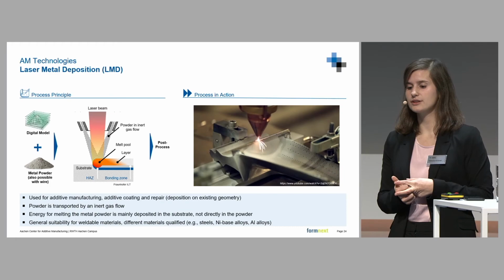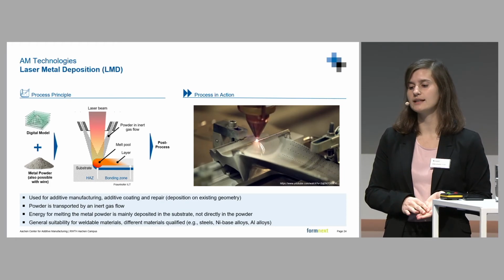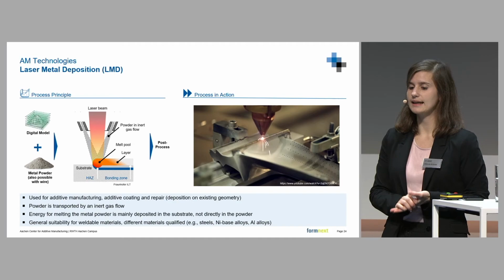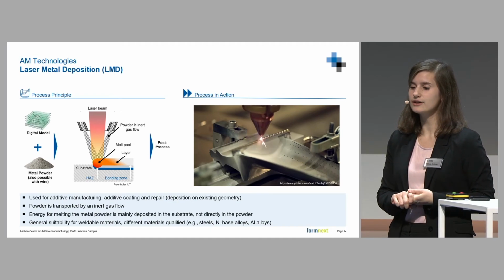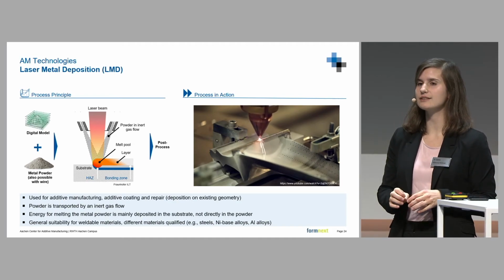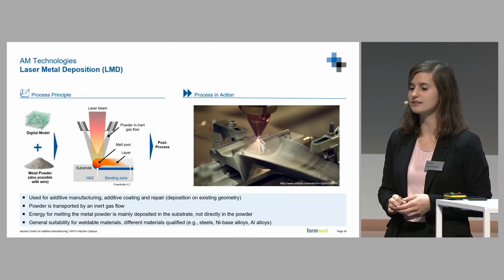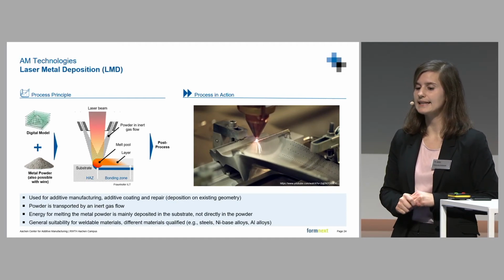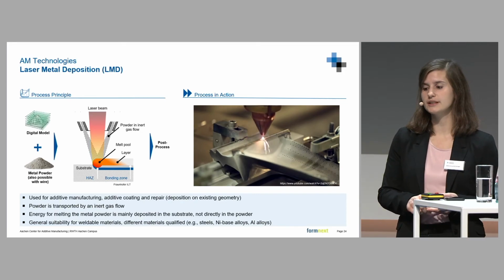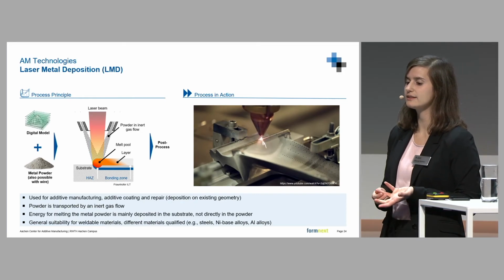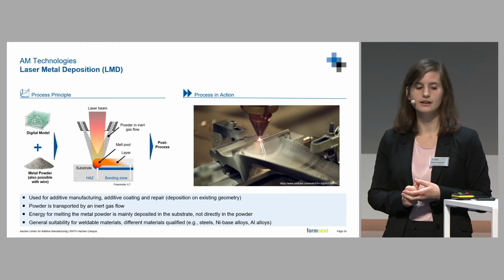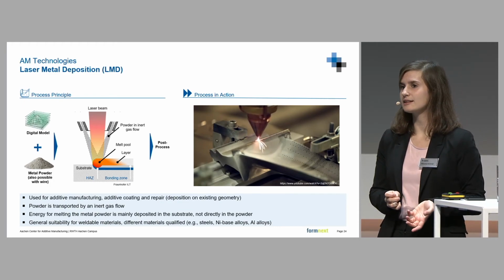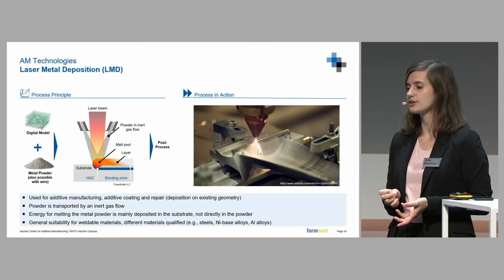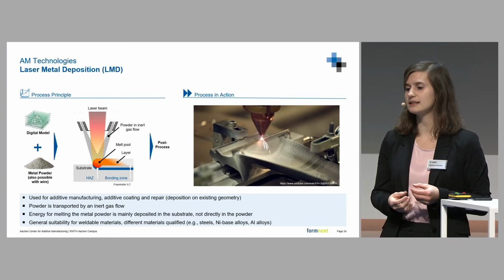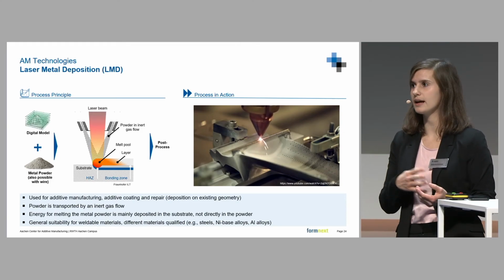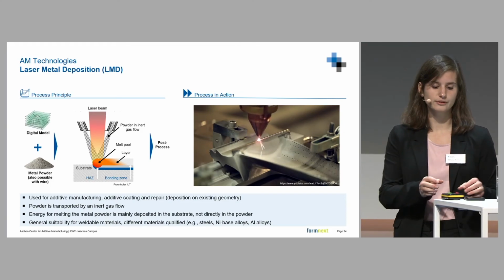And laser metal deposition is mostly used for additive coating or for repair. Like I said, the powder is transported by an inert gas flow, and the energy is mainly deposited in the substrate, not directly in the powder. Again, it has general suitability for weldable materials, such as steels, nickel alloys, or aluminum alloys. It's much faster than laser powder bed fusion, so you have a much higher deposition rate, which is one advantage, but you're limited in the geometry that you're able to process compared with laser powder bed fusion.